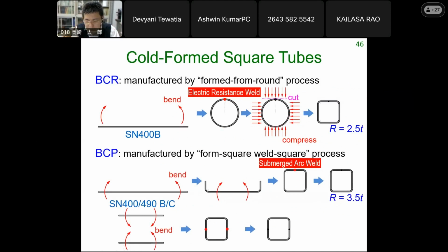These products are made by cold forming, and yes, the effect of cold forming is substantial at these corners. But about two decades ago, there was a lot of testing done for the columns themselves, and also for the beam-to-column connections, to establish that even with the altered properties at this corner, these columns perform well enough. These columns are still designed with a penalty. They're penalized with a reduction of strength when they are proportioned. And we have a strong column, weak beam requirement, so that the action on the columns would not be too big, so that we expect column hinging nowhere.